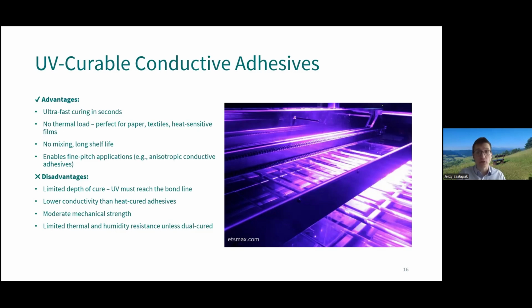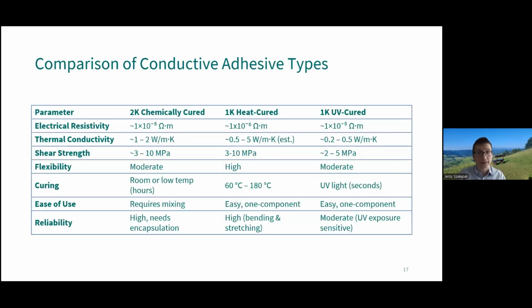But there are limitations here, and they are quite big. Electrically, it's not bad. Comparable to two-component adhesives, maybe even better, although not as good as the one-component ones. But there is quite an issue with the mechanical parameters. Whether you think of conductive pastes, 3D printing, or other techniques based on UV curable materials, they usually require additional curing. And even then, the mechanical properties are clearly inferior to the previous options. Similarly to two-component ones, I haven't found one that would be reliable enough for the uses our team has. All in all, I personally prefer to stick to the heat-cured ones, at least up to date.